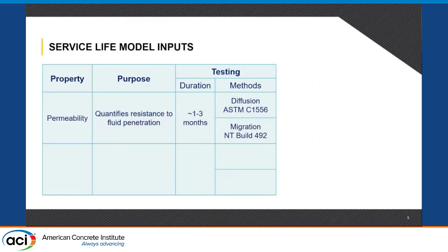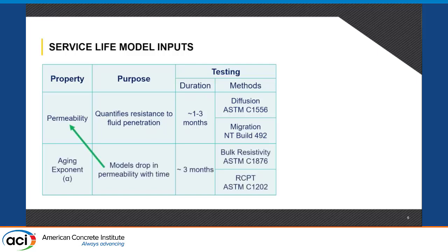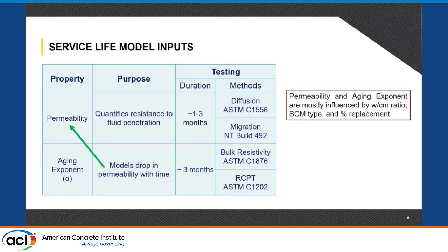So what we do is we model the service life by using a couple of parameters, namely permeability, which quantifies the resistance to fluid penetration. These are a couple of the tests that we do. They're fairly short tests, 1 to 3 months. We also get another parameter, aging exponent, which is modeling how fast permeability is dropping. So permeability and how fast it drops. These are some of the other tests that we do. These two parameters are mostly influenced by cementitious materials, water-cement ratio, and the percent replacement of those cementitious materials, like your fly ash or your slag.